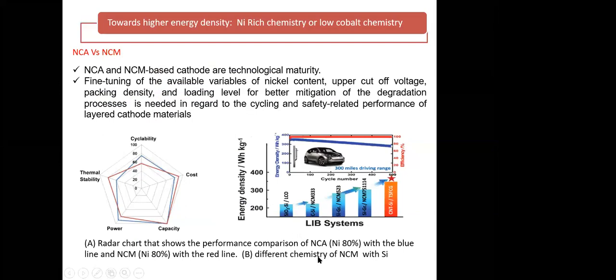But when this NCM is incorporated with silicon, you can make NCM where the nickel is 33%, cobalt is 33%, and manganese is 33. And so reducing the cobalt component and increasing the nickel, like 532, 622, 811, different compositions are coming, the energy density is increasing.